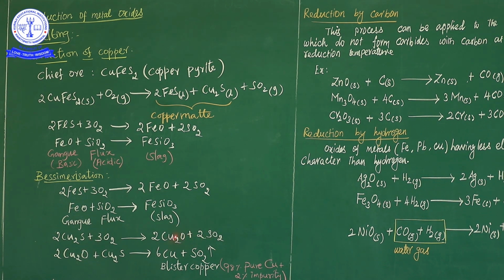Then the cuprous oxide further reacts with the unreacted cuprous sulfide. So the cuprous sulfide here is not completely oxidized. So the cuprous sulfide present in the matte is not completely oxidized. So 60% cuprous sulfide is oxidized to cuprous oxide. So the remaining 40% of unreacted cuprous sulfide combines with the cuprous oxide. So in this step, the cuprous oxide formed reacts with the unreacted cuprous sulfide, it gives an impure copper, and the sulfur is removed as sulfur dioxide gas.